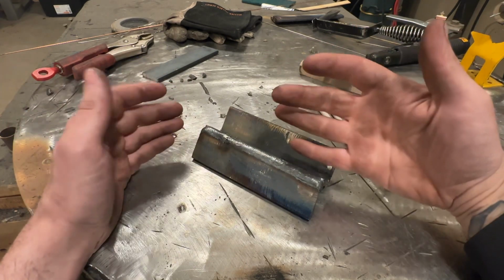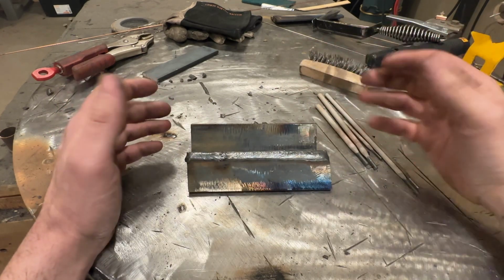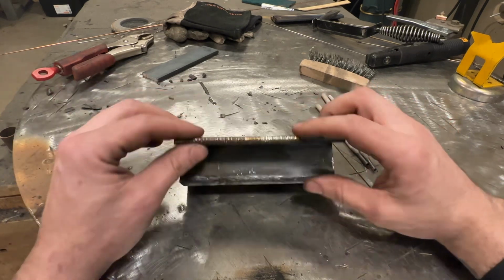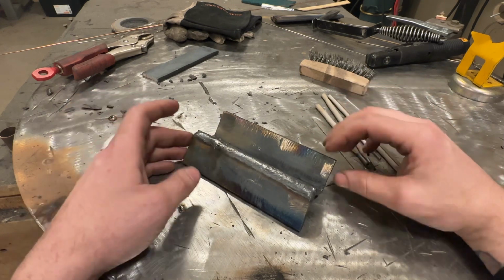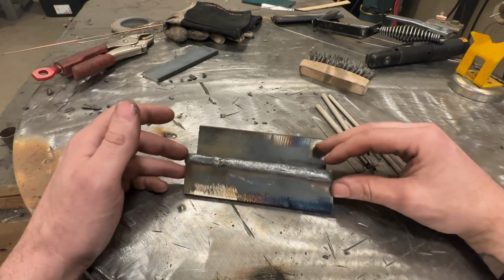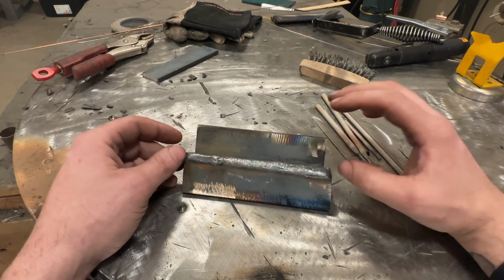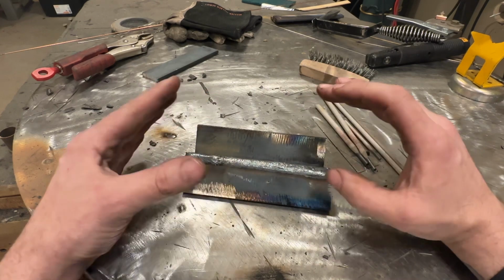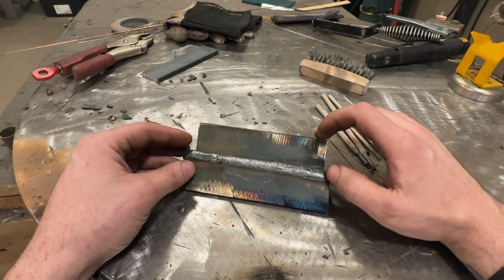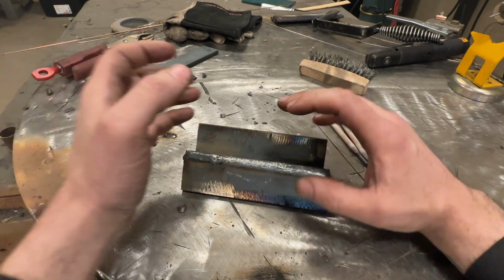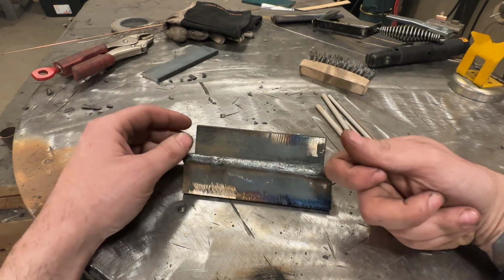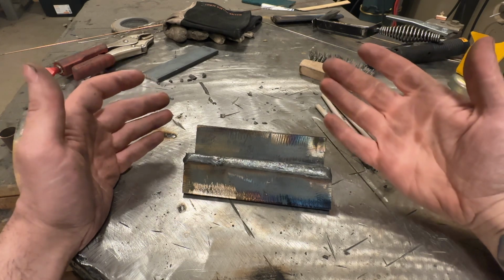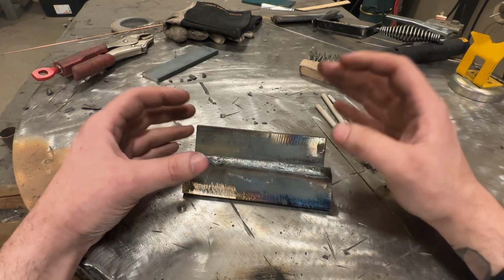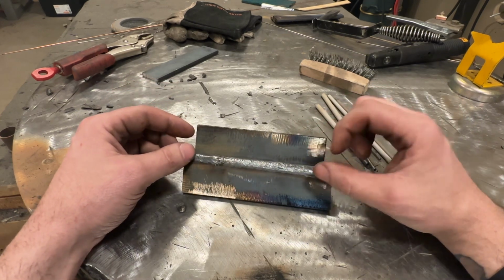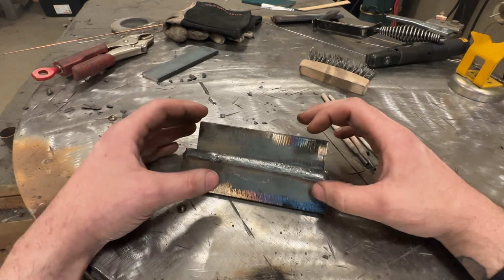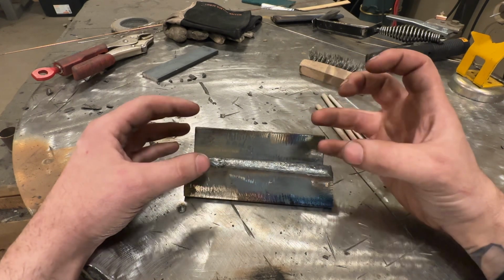There's not enough metal. But one thing that I just didn't grasp for a long time was, well, like you saw here, we just did all these welds, okay, varying amperages, varying rods. What's the right way to do it? Well, I can tell you that the more metal you deposit, generally speaking, and this is in one single pass, the poorer the grain structure of the weld will be, okay? So trying to single pass, and this heavily applies to wire welding because you got a squirt gun there. You can just hold down the trigger and keep putting down metal on metal on metal all day long, right? So stick is a little bit harder to do that, but it still does apply, and generally speaking, the bigger, thicker the weld you put down, the poorer the grain structure. And it has to do with how fast that molten metal solidifies.